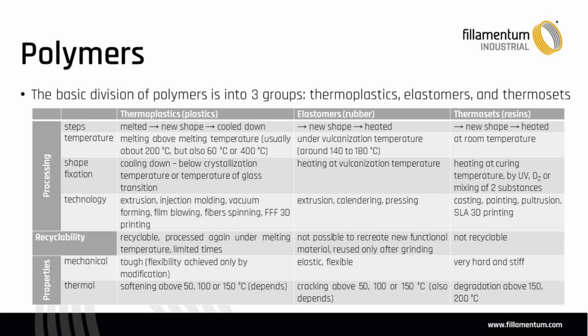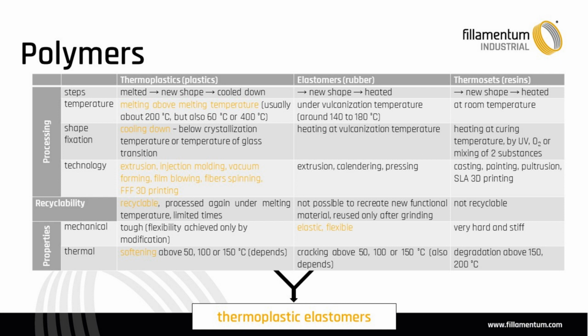Thermal properties are connected with the structure. Basic thermoplastics soften above a certain temperature, for example PLA 50 degrees, ABS 100 degrees, etc. But elastomers and thermosets have a created net that starts degrading at higher temperature. So how is it possible that we can print flexible materials? It's by the connection of thermoplastics and elastomers, in a new group called thermoplastic elastomers. The thermoplastic part gives us the melting and cooling down, the processing technologies, recyclability and softening above a certain temperature, but the mechanical properties are given by the elastomer part.